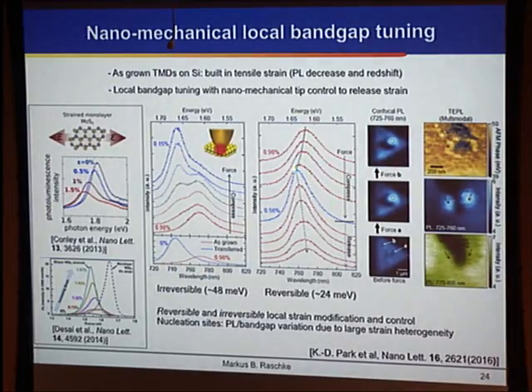And so you see this here, and then we release it again. Then to some extent the material relaxes again, and we go back to the original emission. We can also do this in a non-reversible fashion. If we push hard enough and for long enough, then actually the crystallite detaches from the substrate, and then we get an irreversible release of that strain.